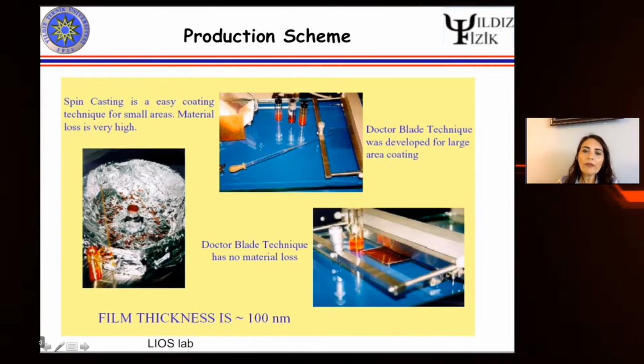On the other hand, we have the Dr. blade technique, which we can apply to large area samples as compared to this one. This is most probably a 1.5 by 1.5 centimeter sample, but here the area is a little bit larger. And you just drop the solution here, as you can see, and this plate runs through this system with the help of an engine, and then you have a uniform film also. It is more advantageous because it has no material loss.